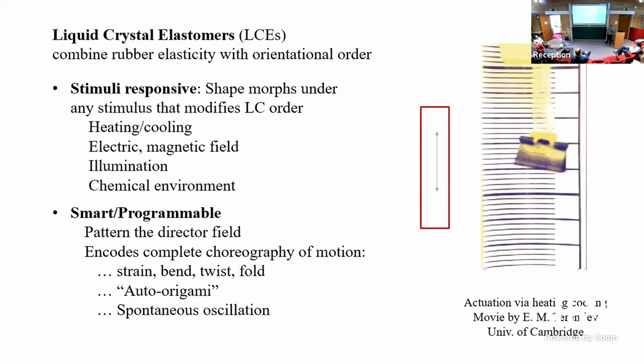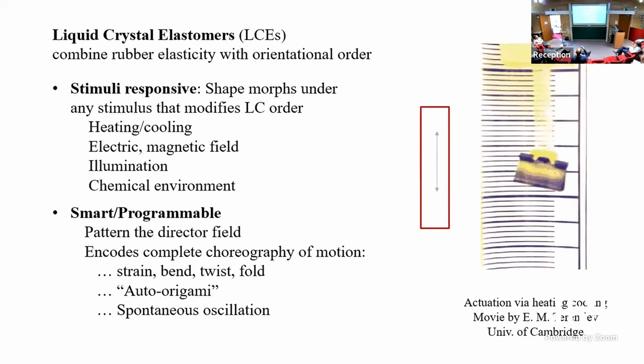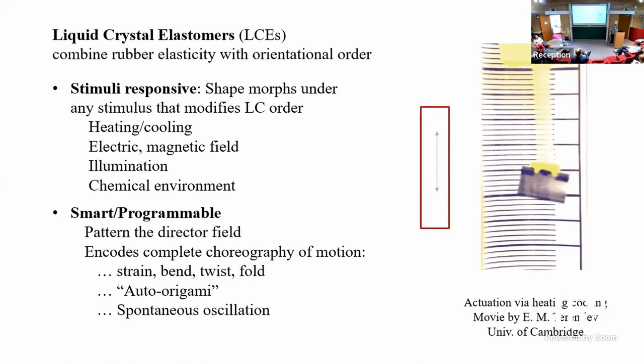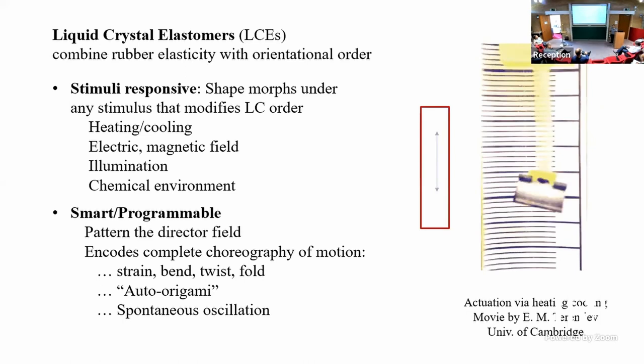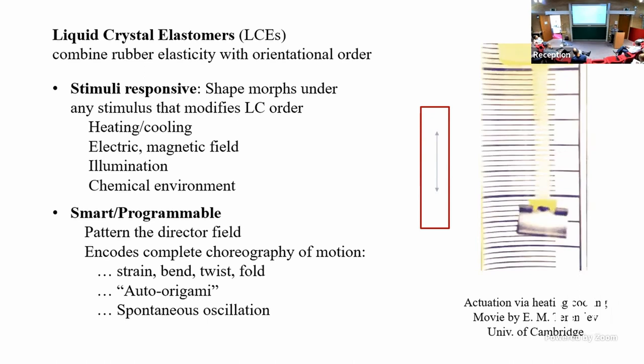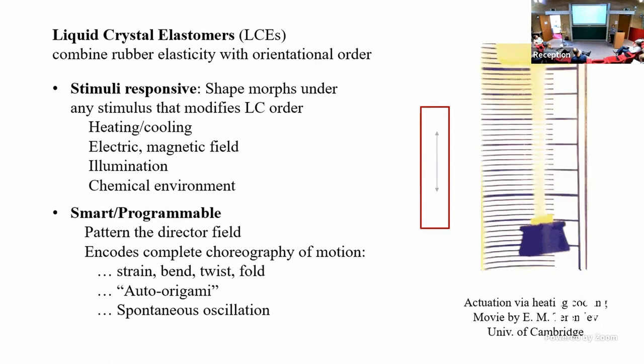In this particular material, the nematic director is pointing up and the material is shrinking and growing along the direction of the nematic orientation. But if you program it by making the nematic director not uniform in the sample, instead of just stretching and shrinking like an artificial muscle, you can make the material bend, twist, fold, do all kinds of things. You can do auto origami, a material that folds itself. And you can also have spontaneous oscillation, typically through a mechanism involving self-shadowing. So, and I will show you one of those.